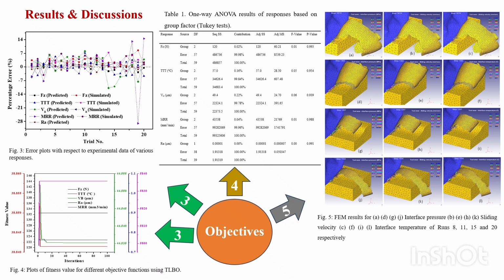Now objective 4, we conducted a Tukey test. Prior to that, one-way ANOVA was conducted to find out whether any significant differences existed among the different groups of experimental, simulated, and predicted datasets. Findings indicated that the p-values for all responses varied between 0.93 and 0.993, which suggested no significant differences between the groups. Objective 5, we can see this is a glimpse of the results obtained for the similar study conducted using MTCVD inserts, wherein flank wear had been estimated using Usui's empirical model.